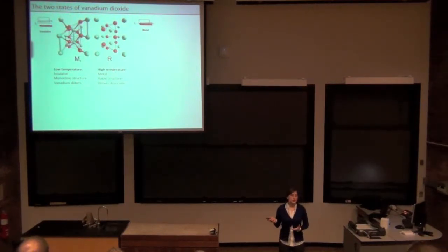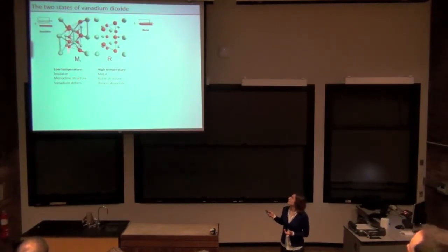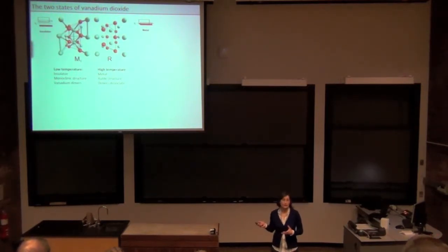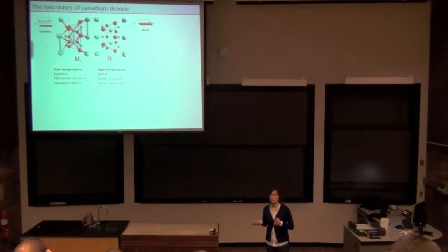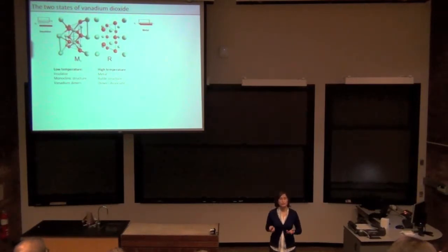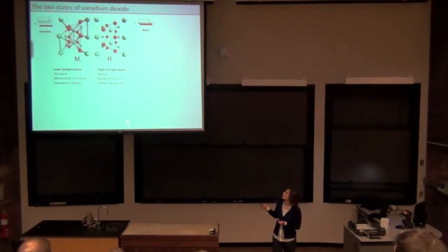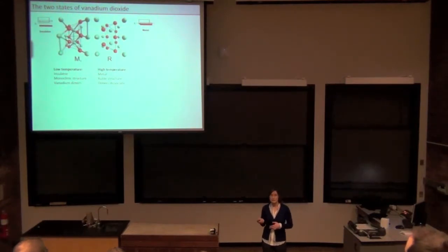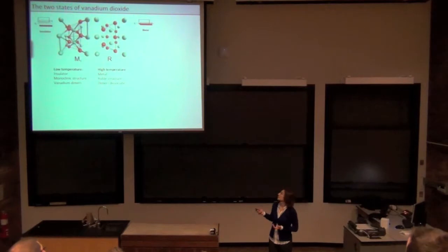But when the temperature increases to about 350 degrees Kelvin, those dimers break. So effectively, you are having your unit cell change. The structure changes from monoclinic to rutile, and thus the material becomes a metal, right? So it has been known for quite some time, but the origin of this transition, specifically the origin of the insulating state, has been debated for decades and is still debated.